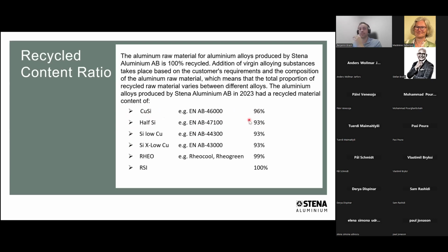So the recycled rate goes down a bit. So here we have to add a bit more of the primary alloying elements. And it's the same 93% figure for instance, the 44,300 alloy, which is also quite common. We have also recently developed these RHEO alloys, and there's a slide that we have a bit more details about the RHEO alloys. And there we have very high recycled content. So there basically we have to add very, very small amounts of primary alloying elements. So that's how it looks like when we look at the different alloying groups.